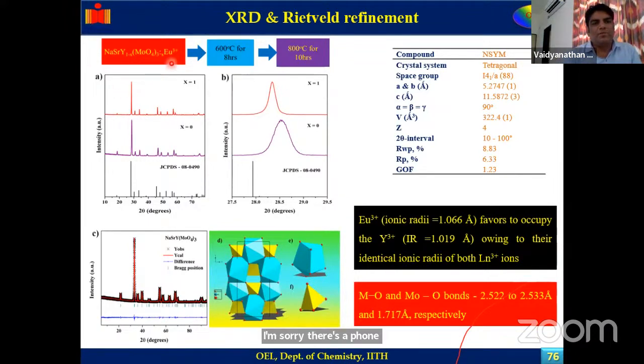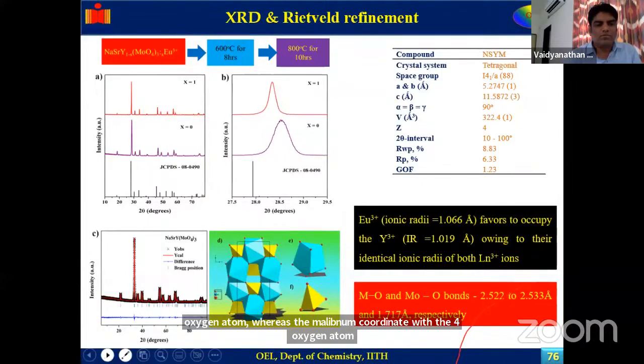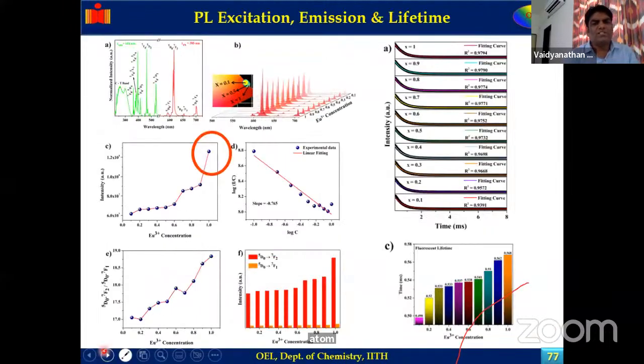Sodium strontium yttrium molybdate, where europium 3 plus is substituted here, crystallizes in the tetragonal structure, having the space group I41/a. In this crystal structure, strontium, yttrium and sodium are coordinated with 8 oxygen atoms, whereas the molybdenum is coordinated with 4 oxygen atoms. What we found is that when you increase the concentration of europium up to 1, we don't find any concentration quenching. The color purity is good, the lifetime is good, and it's a pure red color we get.